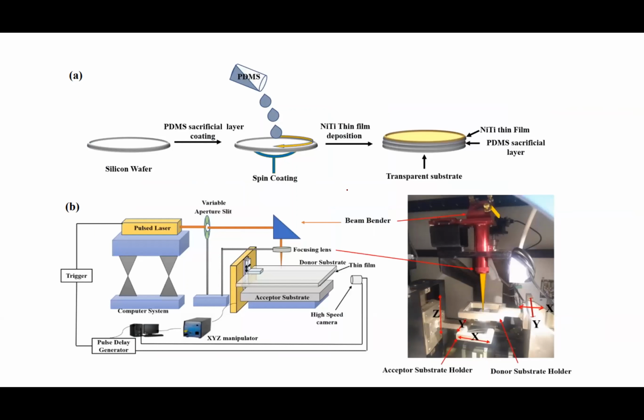Since we have the capability to go for thin structures, we have gone for spin coating, and using spin coating we have prepared our donor film. This donor film and the acceptor film are well interfaced with your laser system, so that even your micron displacement can be easily monitored. So we can go spot by spot. In fact, we have gone for a 99% overlap spot by spot, so that a minute transfer happens and we can have proper features coming out of it. As far as NiTi structures are concerned, this shape memory alloy has its own pseudo-elastic behavior. We were trying to fabricate some kind of strain gauges using these shape memory alloy structures using this system.